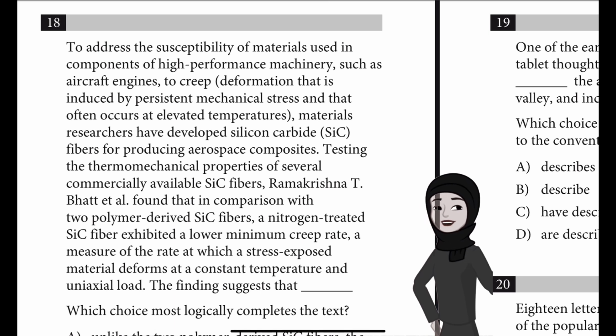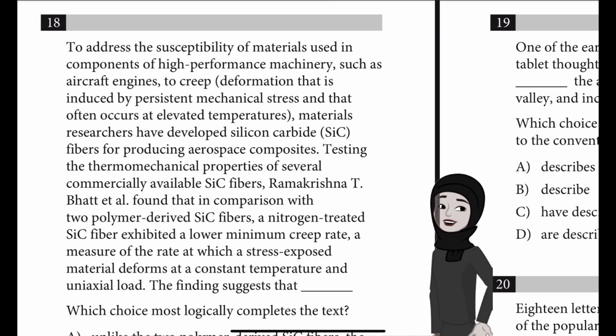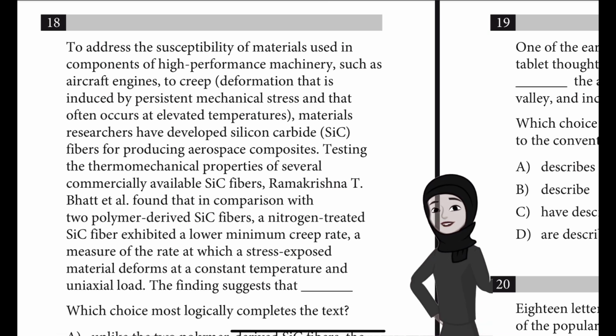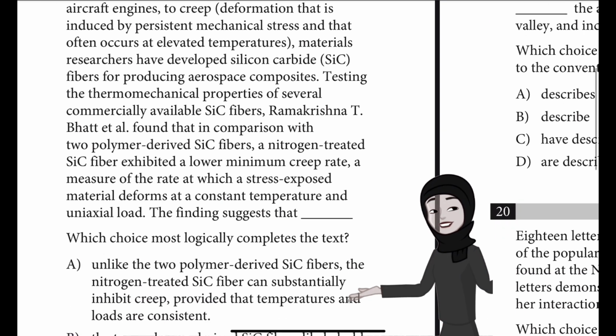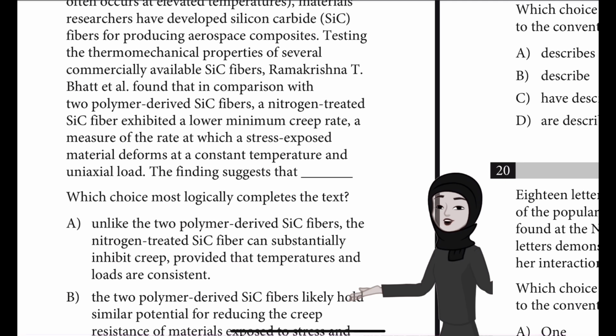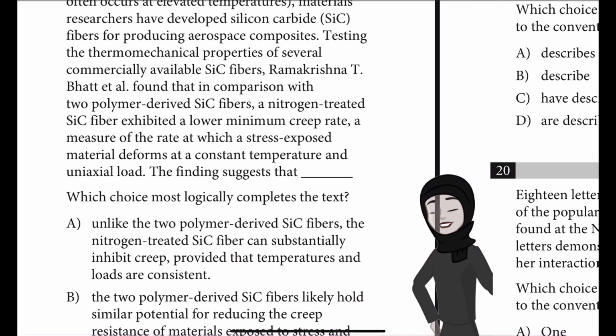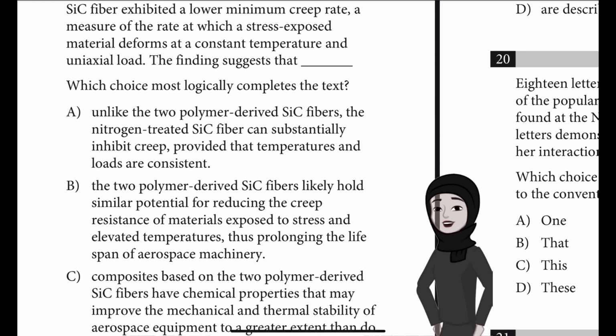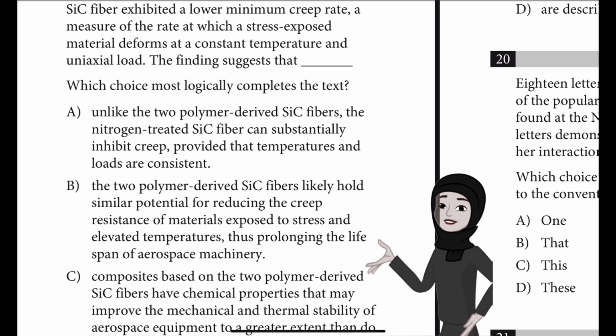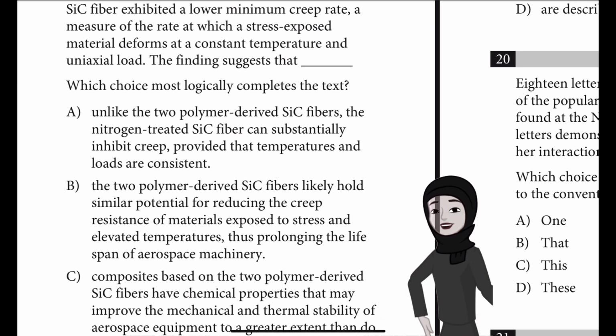Testing the thermomechanical properties of several commercially available SiC fibers, Ramakrishna T. Bhatt et al. found that in comparison with two polymer-derived SiC fibers, a nitrogen-treated SiC fiber exhibited a lower minimum creep rate, a measure of the rate at which a stress-exposed material deforms at a constant temperature and uniaxial load. The finding suggests that blank. Which choice most logically completes the text?